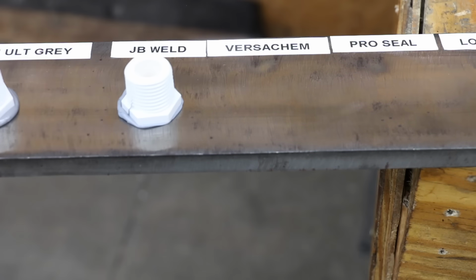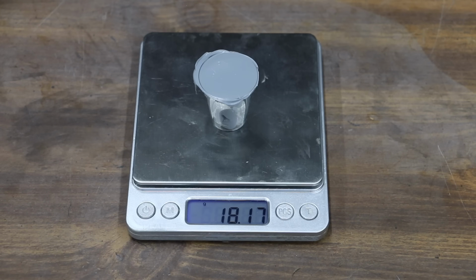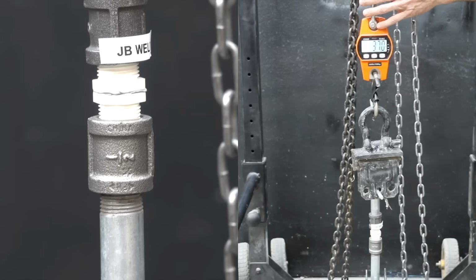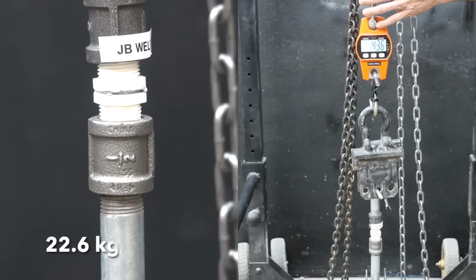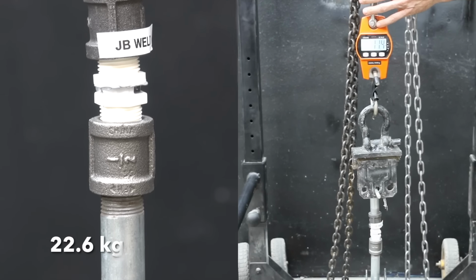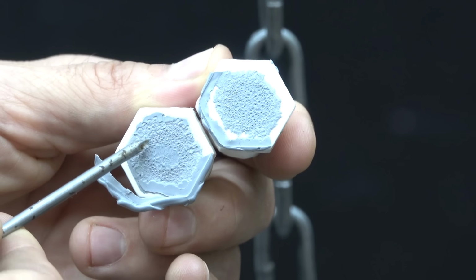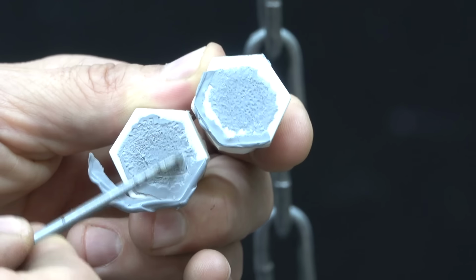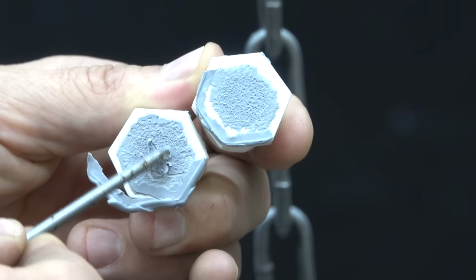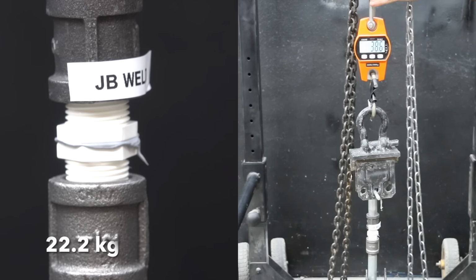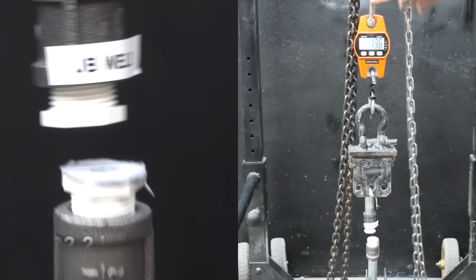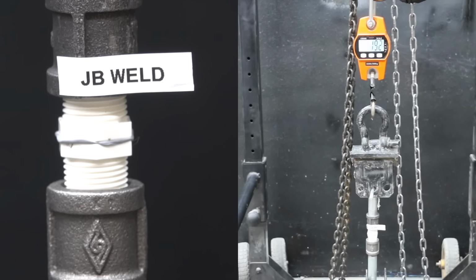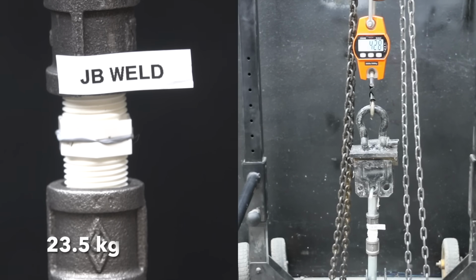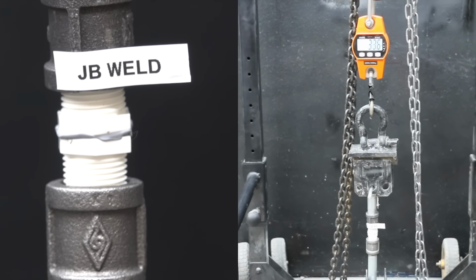And the JB Weld test cup weighs 18.17 grams, or about 2 grams less than the Permatex. And the JB Weld gave up sooner than the Permatex at 49.8 pounds on the first test piece. And the JB Weld is still pretty gooey in the middle. And the width of the cured area is 6.26 millimeters, or just a little bit more than the Permatex. And the second test piece is almost identical to the first at 49 pounds. The third test piece performed extremely close to the first one at 51.8, so less than 3 pounds of variance for the 3 test pieces.